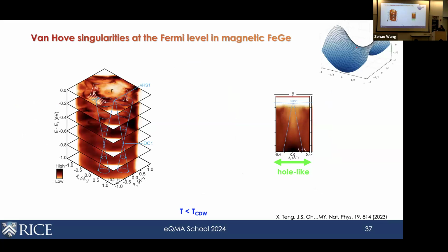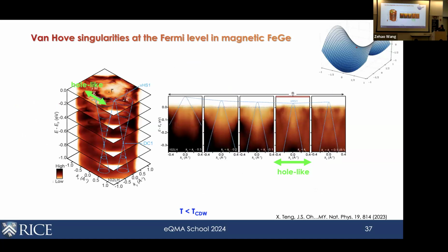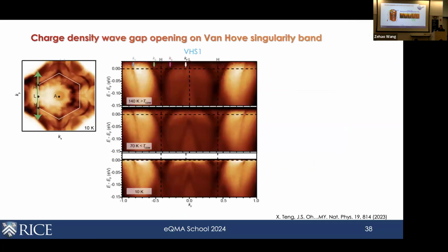So if you take a high symmetry cut, you follow the dispersions along the zone boundary, it looks like a whole band, and you can track where the band top is. And then if you look at the cuts parallel to this green bar, if you walk away, you can also track the top of the Van Hove band. And you can see that in this direction, as we walk in the perpendicular direction, the band top of this whole band tracks out an electron band, right? So what that means is that this is indeed a saddle point that is consistent with expectation of a Van Hove band, right? So in that way, it's reminiscent of what happens in the 135 system with the charge wave. We can do more.